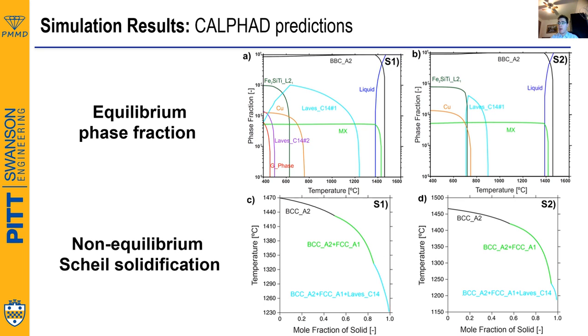And we see that for both samples, the amount of copper and MX phase is expected to be pretty much the same. MX in this system is going to refer to titanium carbides. Also, for both samples, we see that the L21 phase fraction is similar. If we, for example, take 500 degrees C, we see that for both samples, we have a prediction between 8 to 9% volume fraction of L21.